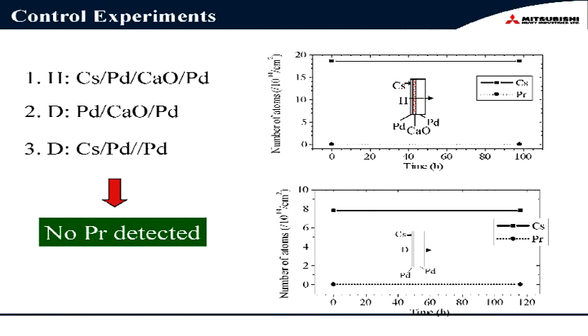These are the results of the control experiment. If we use hydrogen instead of deuterium, we cannot see any change of cesium, and also we cannot see any praseodymium. And if we omit cesium, we also cannot see any change. And if we omit this calcium oxide, we also cannot see any change. So we can say that deuterium, the multilayer thin film, and elements such as cesium are necessary to observe this phenomenon.